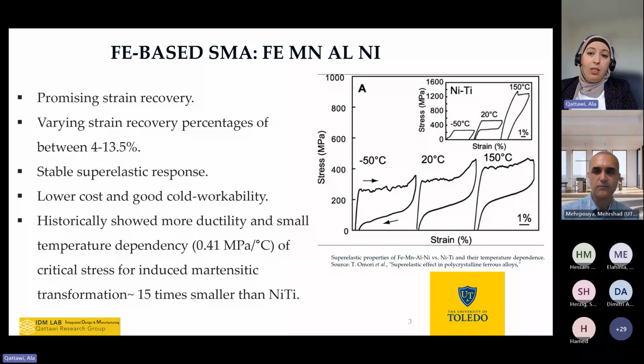So technically, if you can see the figure on the right, mostly the nickel titanium will reduce its efficiency in performance as we increase the temperature. And this is not the case, as has been proven for the iron shape memory alloy. So there is a potential if we can understand how to manufacture this alloy system carefully and understand the correlation between process parameters and the microstructure, there is a window where we can leverage this phenomenon in the alloy system.